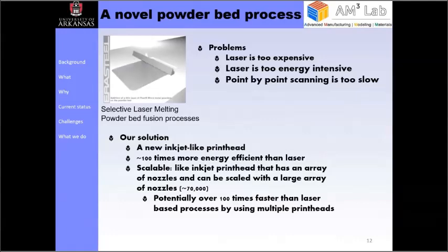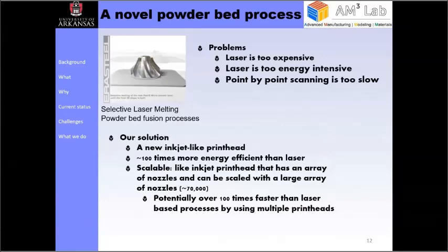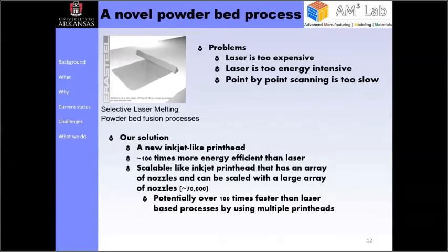I cannot talk too much about our current solution in more detail yet, because everything is still at a very early stage. But I will briefly give you an idea of what we're doing. We are developing an inkjet-like print head, which is scalable, using multiple nozzles instead of one single point. So you can print a whole layer at one time. Based on our calculations, it is about 100 times more energy efficient than a laser. And because it's scalable, we can hopefully scale it to a very high speed.